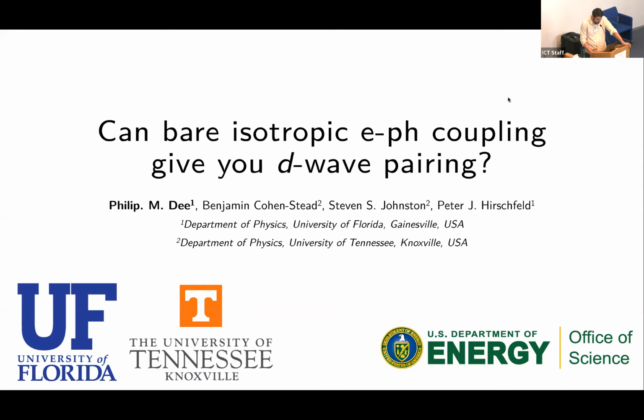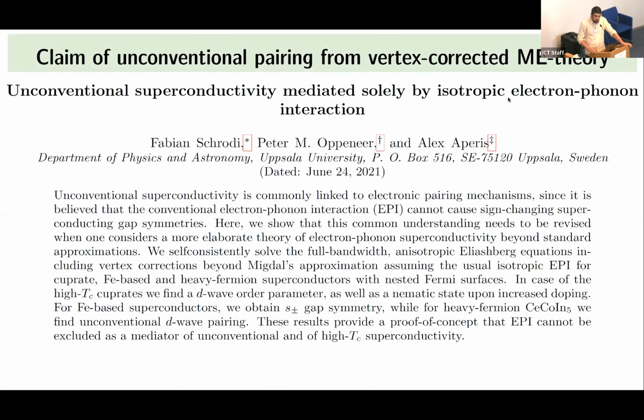So the idea is that in the Migdal-Eliashberg formalism, there is a primary approximation, which is Migdal's approximation, sometimes referred to kind of tenuously as Migdal's theorem. And for a long time, people have been interested in what happens when you add corrections to this theory. And so a paper that kind of intrigued me and some of my collaborators more recently was this one by Schrödi et al., which said that using a bare electron phonon coupling, they were able to use vertex-corrected Eliashberg theory to find unconventional pairing symmetries.